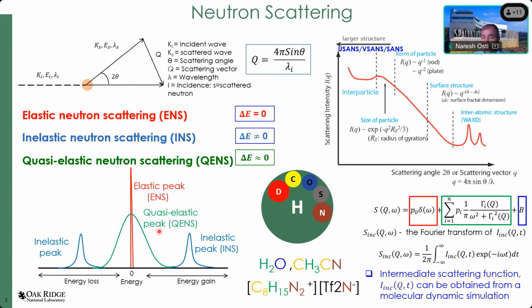In this technique, what we do is measure the dynamic structure factor, which is the combination of the elastic component, the inelastic component, which gives you the background, and the quasi-elastic component. This quasi-elastic component can be Fourier transformed, from which you can get the intermediate scattering function. That intermediate scattering function can also be obtained from molecular dynamics simulation. That means this is the beauty of the technique, where you can connect the experimental approach with the theoretical approach. That's why this technique is very powerful for resolving the dynamics of hydrogen-containing material.